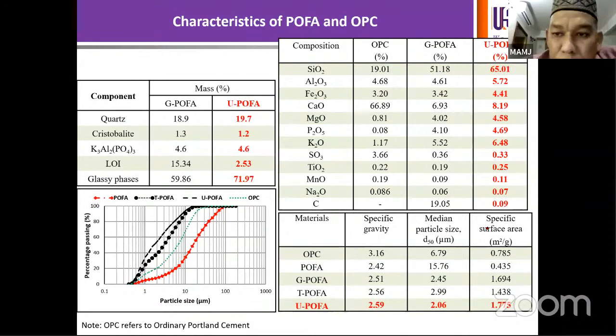All right, so some analysis has been carried out on the material, in terms of chemical composition, as well as physical properties, particle size distribution, and specific gravity. When we compare these two types of POFA, G-POFA, meaning after milling, and the U-POFA, which is the final product, we can see a significant increase in SiO2 and also an increase in Al2O3 as well as CaO. That increase is in line with the reduction in carbon content, or combustible carbon content, which reduced significantly from about 19% to less than 0.1%.